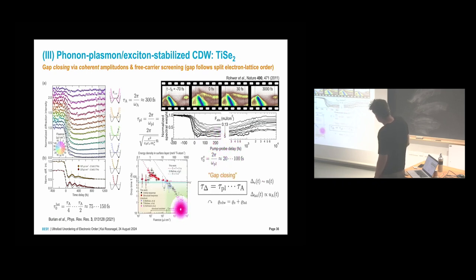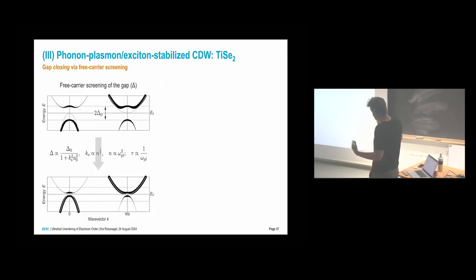And if you bring the time scales together, you can see at strong, high fluences you have these electronic dominated processes. At lower fluences, it becomes phonon dominated. And then here you have a gap closing happening on multiple time scales, a fast electronic component and a slow lattice component. And here, this is the unique case where the charge density wave really is two things in one, an electronic thing and a lattice thing, and not everything is directly tied to the lattice. So here is how, yeah?